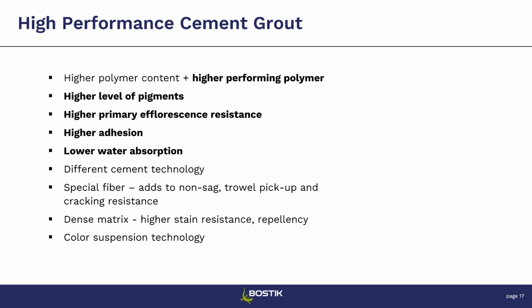So with a high performance cement grout, there are a few things that are needed, which is the addition of the polymers that we talked about before that are added to the formula. The higher the polymer content, the higher performing it is, so the stronger it is. There's a higher level of pigments. There's more efflorescence resistance to it, so it's higher than one that does not have polymer modified content. There is higher adhesion. It does absorb less water, so it's a little different from a pure cement technology if it is polymer modified. It has a special fiber. That special fiber adds to the troweling and pickup and crack resistance of the grout once it dries. There is a dense matrix, so it's a higher stain resistance versus a non-polymer.